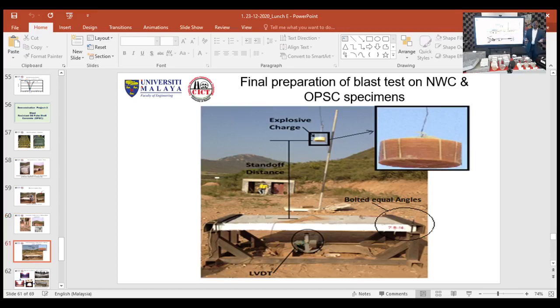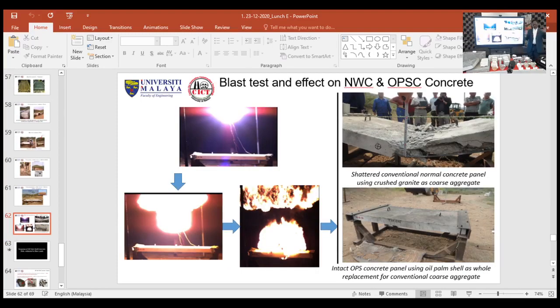And you can see that the standoff distance between the blast panel, the oil palm shell or normal weight concrete panel, and the explosive is only 1.5 meter. The standoff distance is quite important, as the explosive or the impact or the pressure waves depend on the standoff distance. So the standoff distance is quite close, 1.5 meters, and you can see the contrasting features of these two slabs. On the left hand side, we see the initiation of the blast through remote. Then the blast is accompanied by fire. There's a pressure and a lot of impact on the slab. So there's impact, there's pressure, and there's fire. The slabs have to withstand all these three.